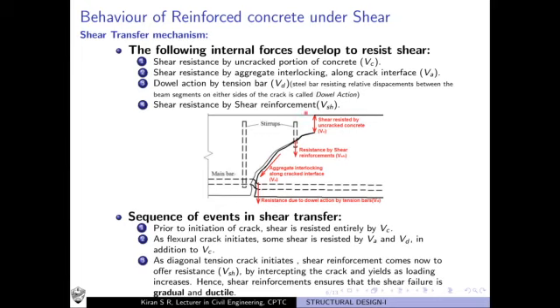Now since this part is resisting a part of the shear force, there are other parts which are also capable of resisting shear. You know that this crack has occurred, okay, and this has divided the beam into two segments. There is one portion on the left side of the crack, there is another portion on the right side of the crack. As a result, there is a relative movement between the two segments. The second segment will move relative to the first segment. As a result, aggregate interlocking occurs at the interface of this crack. Interlocking or frictional resistance will be offered by the aggregates of the concrete between the two segments, and this will also resist shear. So that we call shear resistance by aggregate interlocking along the crack interface, represented by the notation V suffix A.